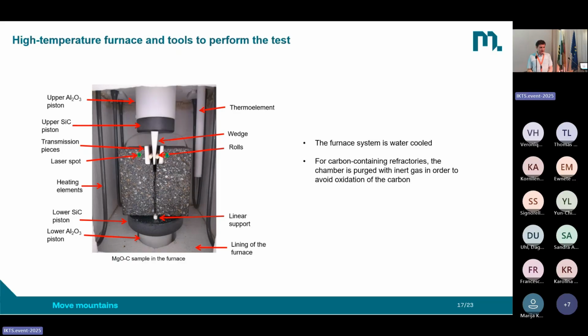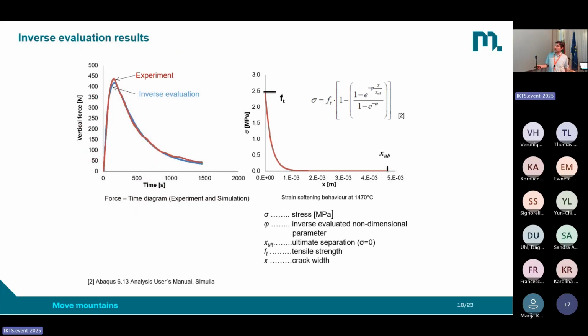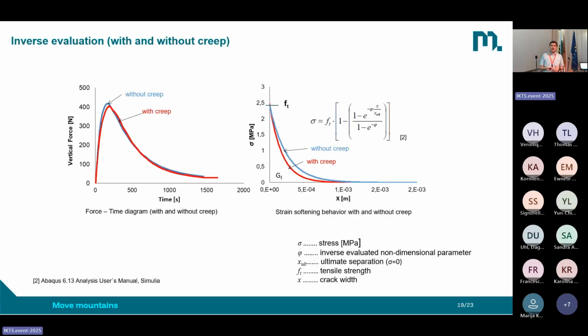If we do it at high temperature, then again, we could do our inverse evaluation. You see in red the experiment, in blue the inverse evaluation. Again, there's a good fit. We can apply here for the softening behavior an exponential law, how it is implemented in Abaqus already, and see that we can get a good fit for high temperatures as well. But this is without considering creep.